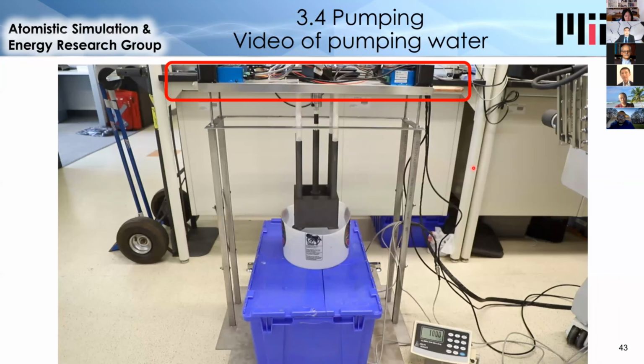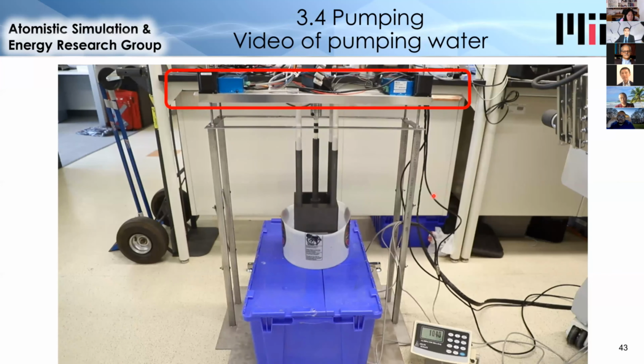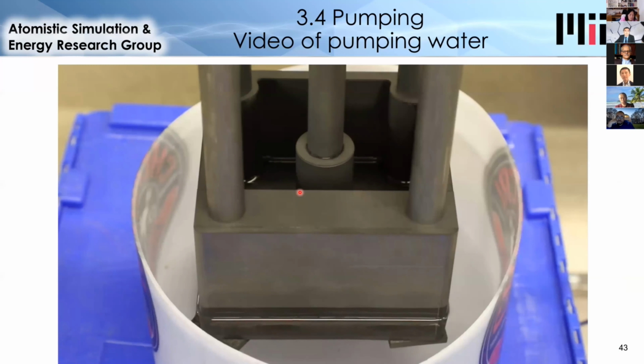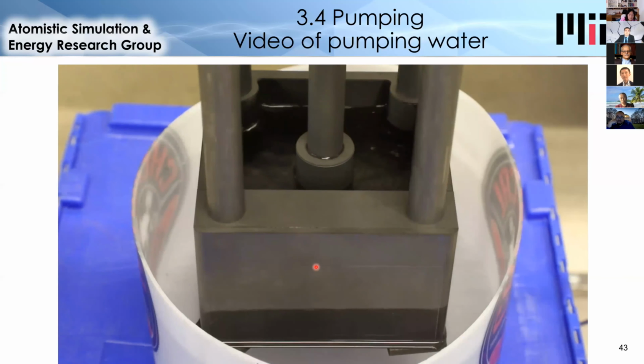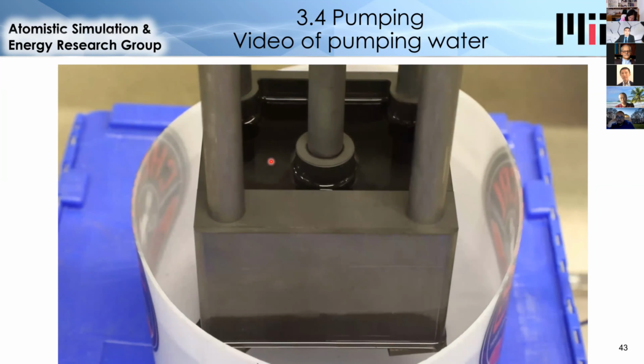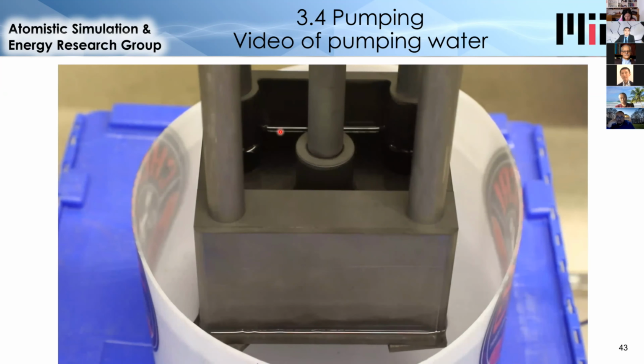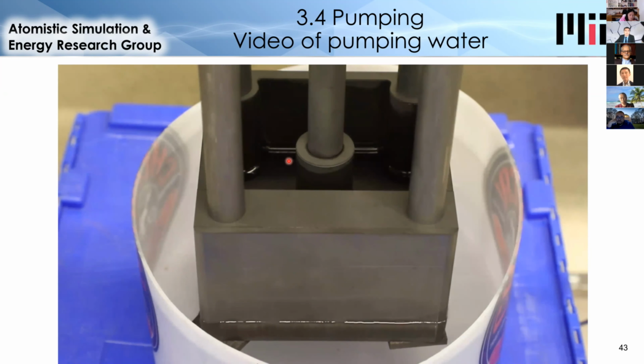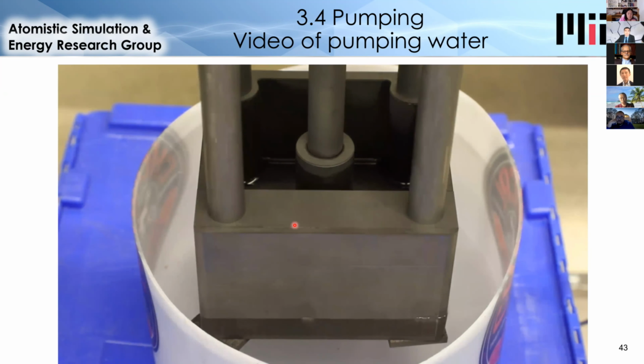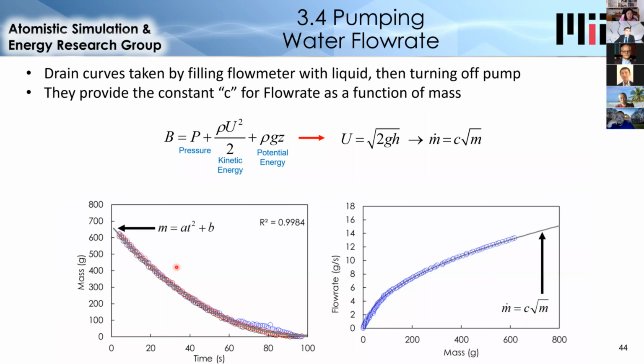So first, I ran a test with water to determine the effect of this. I lowered the pump into water, turned it on, it fills up with water, it gets heavier, turned it off, and the water drains out. And it's while the water is draining out that I can calibrate the flow meter. So if we look at this curve on the bottom left, this is just raw experimental data of the mass of the pump versus time. So it's decreasing as the water drains out.